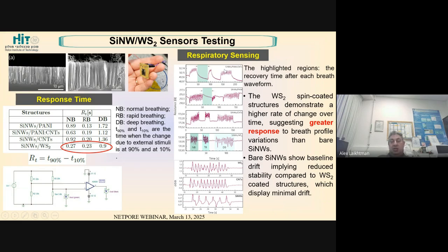So here you can see measurements of resistivity for breathing of normal people for different regimes. This is a derivative, and the spin-coated WS2 structures demonstrate a higher rate of change over time, suggesting greater response to breath profile variations than just silicon nanowires. And they show baseline drift implying reduced stability compared to WS2 coated structures. So WS2 coated structures provide a great advantage from this point of view.